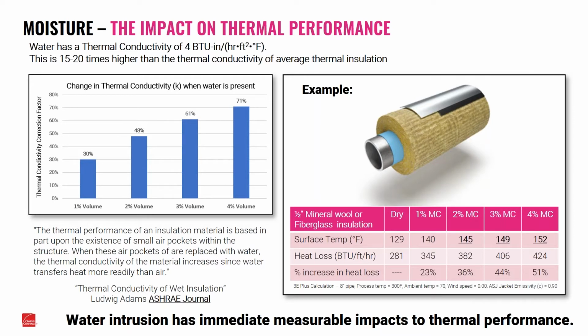Now, as we go each subsequent step, as we go from 1 to 2 to 3 to 4%, we can see that surface temperature actually increases. And we're looking at what a 23-degree increase in temperature just of having insulation that has 4% moisture content. And we have a heat loss that's 51% higher than what we originally started with. So this is a real deal. And just because it's a little bit of water and we think, we have a hot system, it'll evaporate it off, it's a bit simplistic.